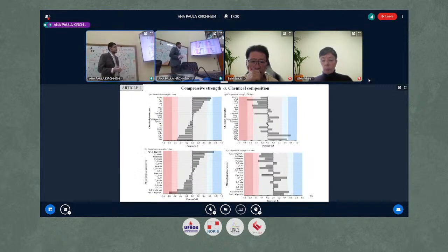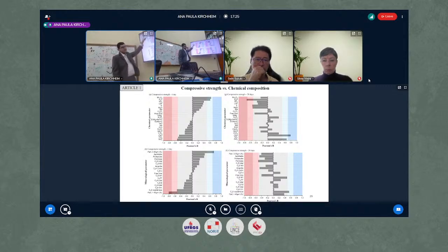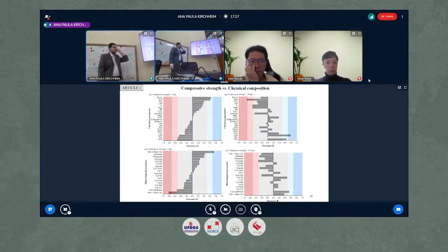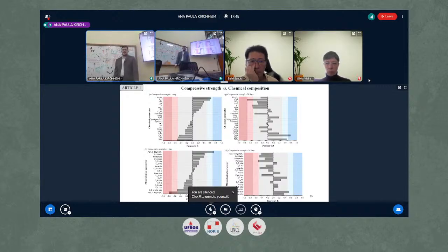In terms of compressive strength at 1 day, we see here that the most influence was again sodium and potassium oxide, positive at 1 day and negative at 28 days, as also observed in the literature. We also saw an influence of manganese oxide that we could not explain. Perhaps there's a correlation with sodium, potassium, or something else that we couldn't see, but it's something interesting to investigate.